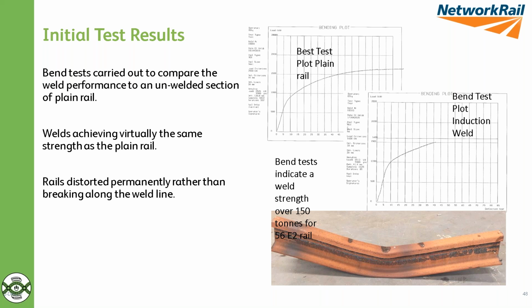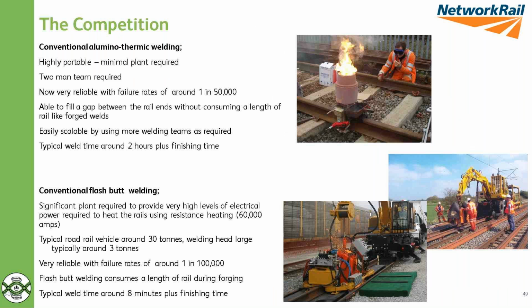So some advantages perhaps there over flashbutt welding, and there's less risk of getting defects within the fracture face or defects within the weld fusion, because there's less heating and melting at that point. It's a more controlled heating. But that's what testing today is, to produce a number of welds under different conditions, to do the bend testing in a real environment. Currently, it's just been doing short samples in a laboratory, but this is testing now in a real environment under real weld conditions, making sure we get the same.